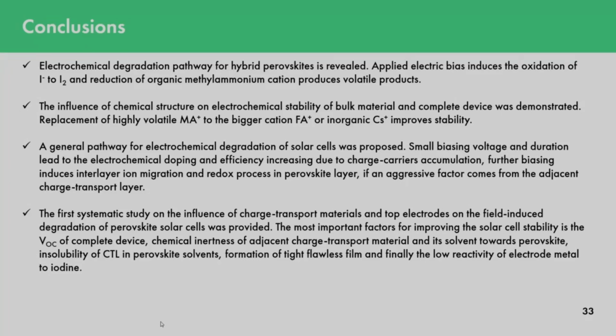So we also provided the first systematic study on the influence of different charge transport materials on the field-induced degradation of solar cells, and we can imply the most important factors for improving the solar cell. First, try to provide a solar cell with as high an open circuit voltage, or as high a maximum power point voltage, as possible. Another important factor is chemical inertness of adjacent charge transport materials and their solvents towards perovskite, and of course insolubility of charge transport materials in perovskite solvents, so they won't be partially flushed away, and of course formation of a tight, flawless film, as was probably the case for PTAA material, which formed a polymer.